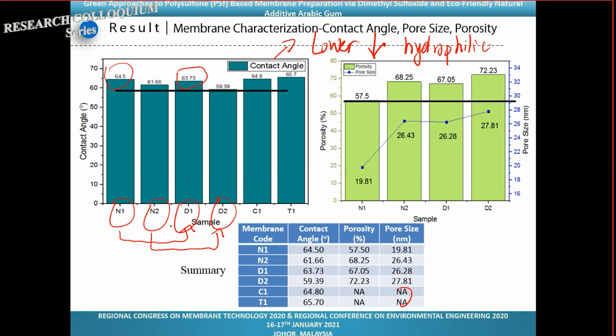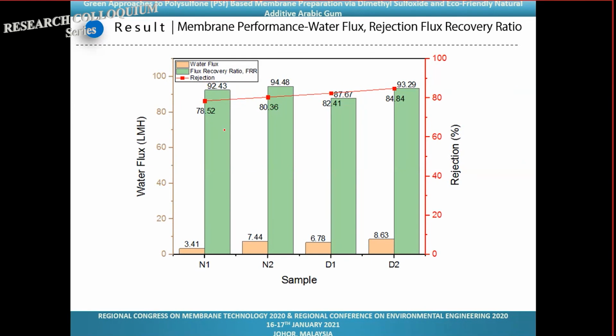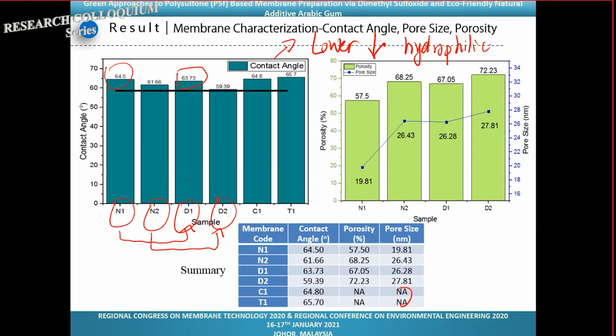As for the N2 and D2 result here, we can see that D2 is lower than N2. So it is shown that this D2, the membrane that was fabricated using the DMSO, also shows a better hydrophilicity. And owing to this improved hydrophilicity, the porosity and the pore size increase accordingly. So as you can see from the curve itself.